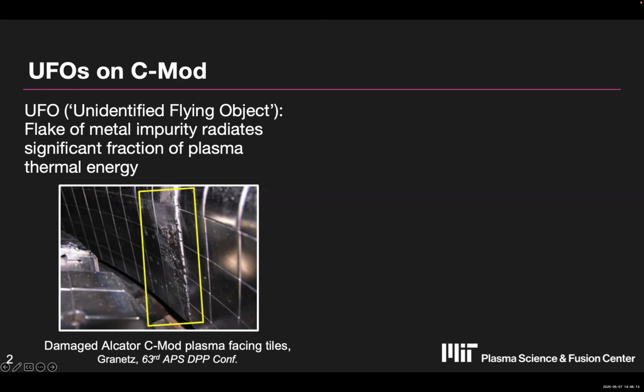And so here you can see on a picture of CMOD the suspected origin of a UFO disruption, where you can see that a piece of the wall got misaligned. You can see there's this leading edge in the yellow box, which experienced an unusually high heat flux since that piece of wall was exposed. And you can see there's some melting, probably some liquid molybdenum droplets entered the plasma and quickly caused a disruption.